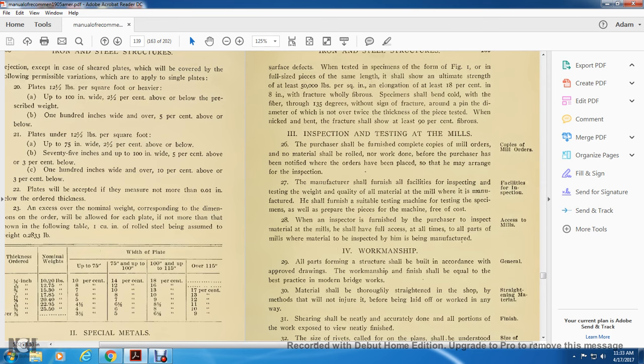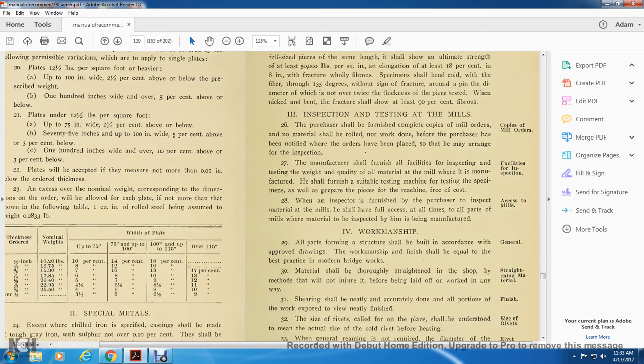The test is specified with the form of the ticker at one end, the full size piece with the same length, but there shall be some ultimate strength of at least 50,000 pounds per square inch, with elongation of at least 18% in 8 inches, with the fracture wholly fibrous. The specimen shall be bent cold, while the fiber is 135 degrees without the sign of fracture around a pin of a diameter not over twice the thickness of the piece tested. When nicked and bent, the fracture must show at least 90% fibrous.